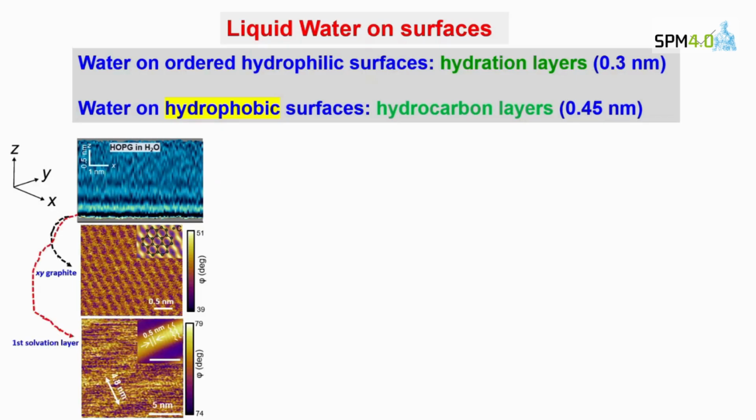And when you do that, you get these parallel structures. And when you go to the molecular resolution, these structures are separated by 5 angstrom, which was actually the size of the layer. What we are looking at here is not the perpendicular direction, but this direction, just inside the layer. How the molecules which are there, that were supposed to be water but are not water, are separated: they are 5 angstrom.